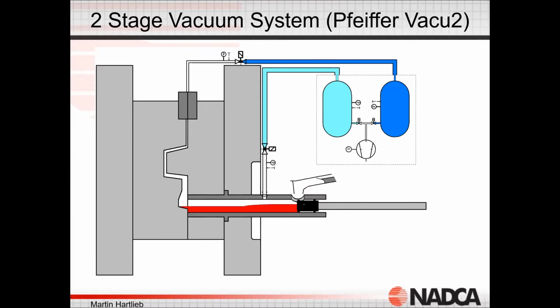This is the injection piston. As the piston covers what we call the pour hole and closes the pour hole, we then turn on the vacuum system. We have a vacuum system on the chamber or the shot sleeve, and then we have a vacuum system in the mold going to vacuum tanks. So we have a large vacuum reservoir that we turn on, and this is now moving forward. The metal is moving forward into the cavity. As we pass this point, the vacuum in the chamber is shut off, and we have these vacuums in the die still on. So we're still drawing vacuum here. This one is turned off.